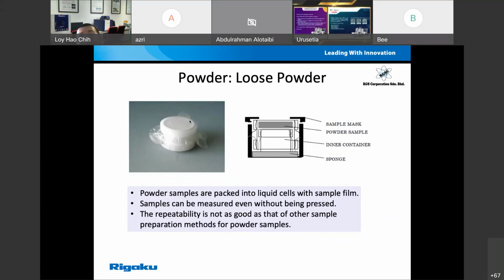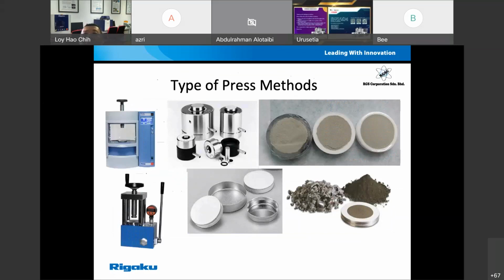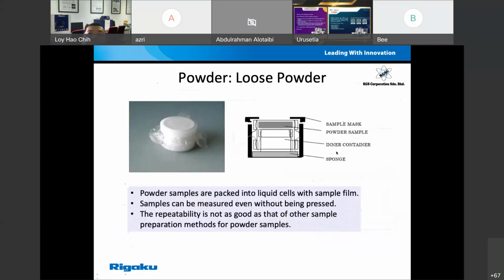For those kinds of cases, normally what we recommend is that you press your samples. When you press your samples and put them inside the XRF, we can measure directly. There is no protection, no film barrier which is going to absorb your XRF energy. Okay.